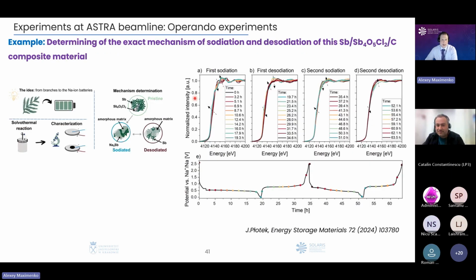The same, for example, you could investigate what is going on with electrode material in your batteries during charging and discharging. Here you could see the XANES spectra measured at sodium-ion batteries at the antimony L3 edge during the charging and discharging process, and it allows us to investigate what kind of shrinkage of the material appears and why it is going in such a way. If you are interested, you could follow this publication. I could say that it is quite interesting.